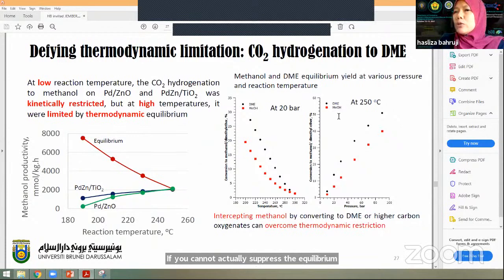But when we try to compare the theoretical production of DME and methanol, we can see that DME has a much higher threshold, so that we can always push the temperature a lot further and produce these oxygenated products at a much higher temperature. Because reducing the reaction temperature is quite difficult, because CO2 is a very stable molecule that requires quite high temperature to activate.